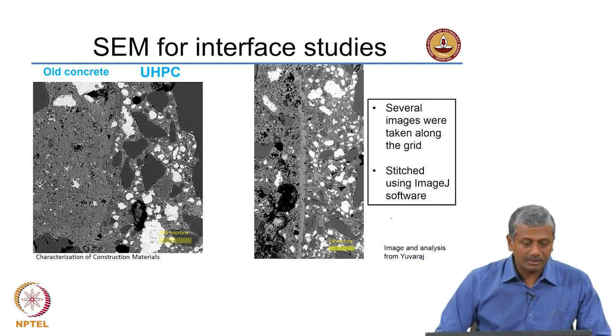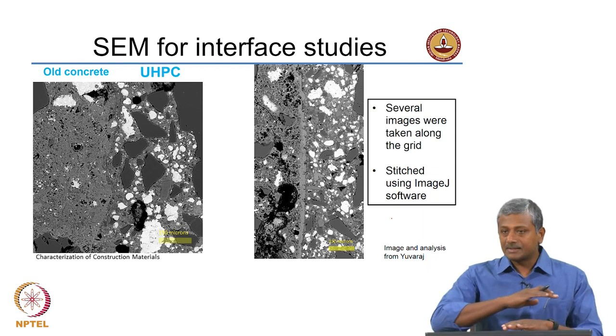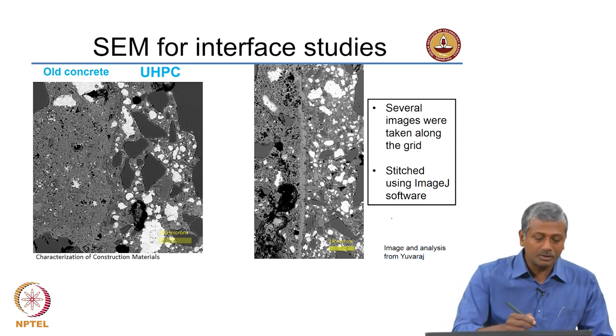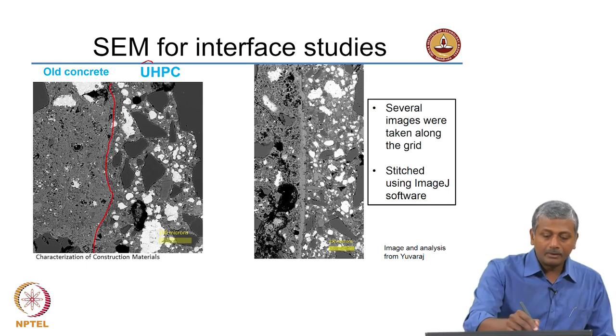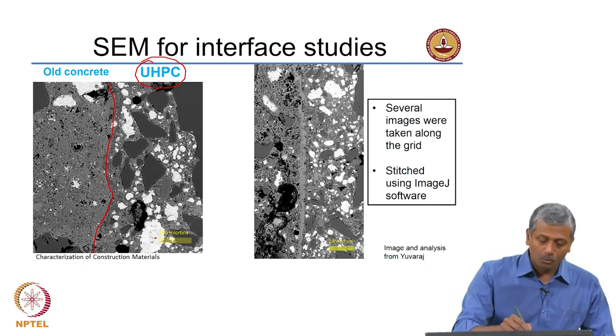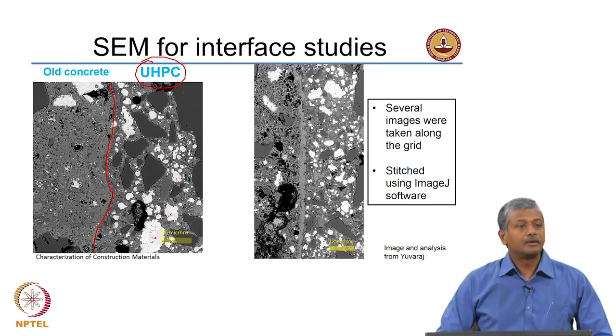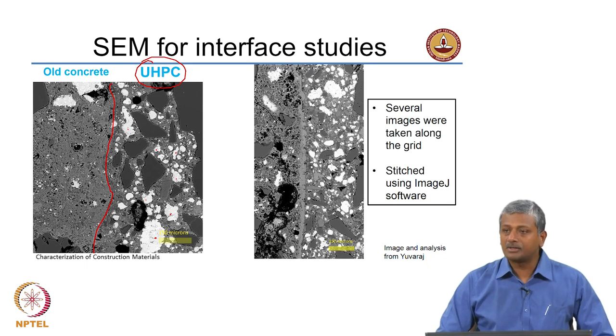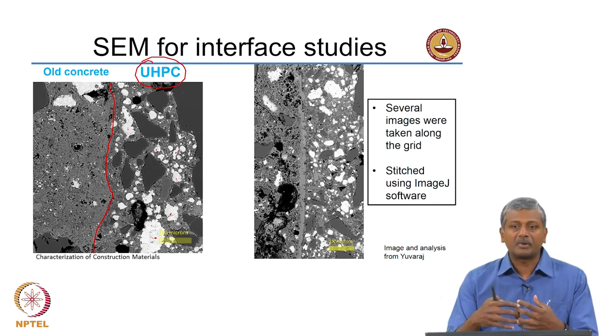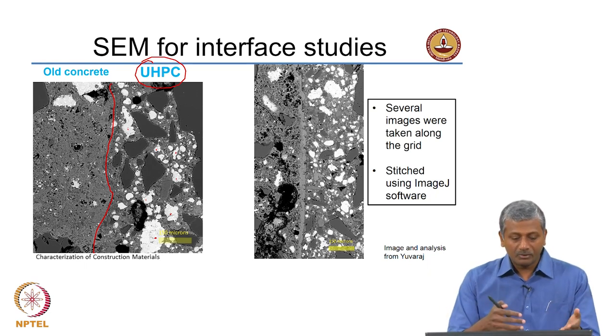This is an example of studies done in our lab where we looked at ultra high performance concrete as an overlay for existing cracked old concrete beams for repair. You can clearly see the interface between the old concrete and the UHPC layer placed on top. A distinguishing feature is that UHPC has a lot more unhydrated cement due to its very low water-cement ratio — most of the cement does not get to hydrate. UHPC achieves a dense packing through careful particle size distributions, so the porosity in UHPC is much lower compared to the old concrete.